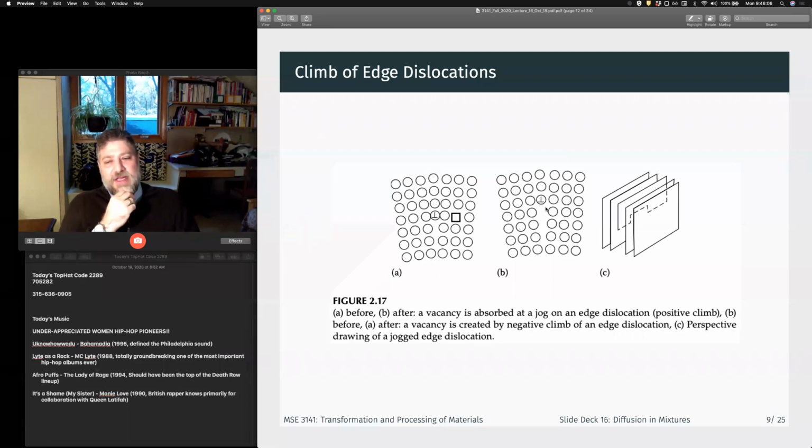So what's my dislocation density going to be about? Are you talking about like per crystal? The dislocation density is usually given in line length per unit volume. So it has units of per meter squared. Right, so what's a low dislocation density? Right, oh, okay, cool. You guys learned something new today. So it's about 10 to the 12th per meter squared, right?